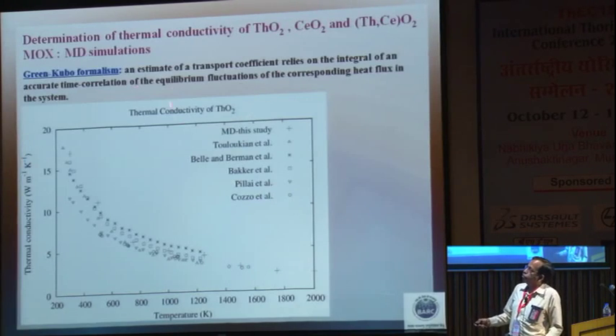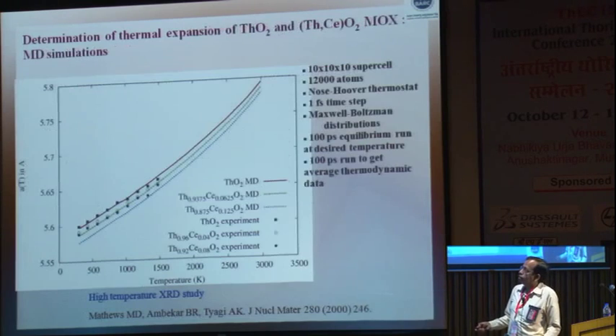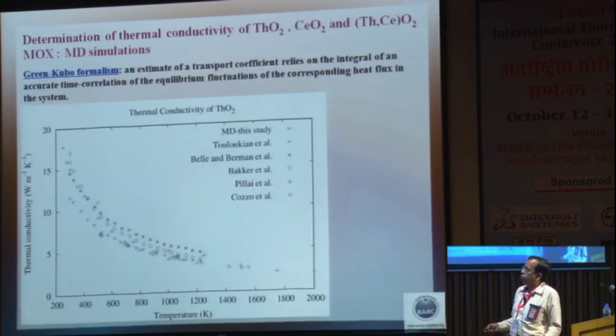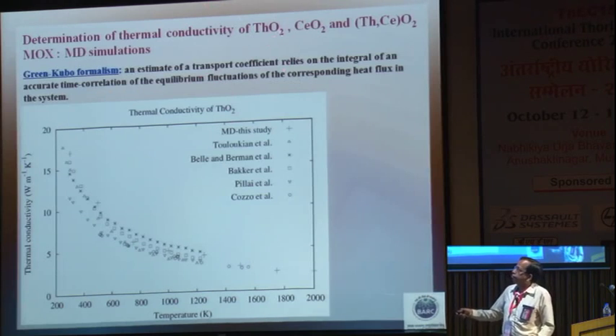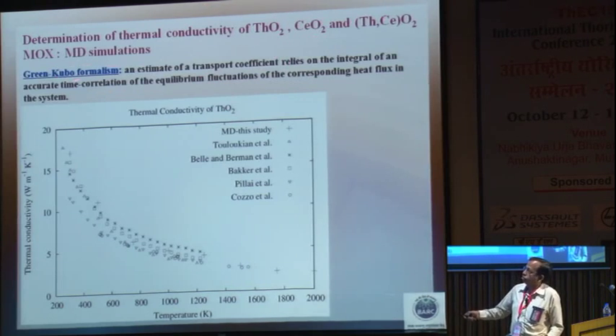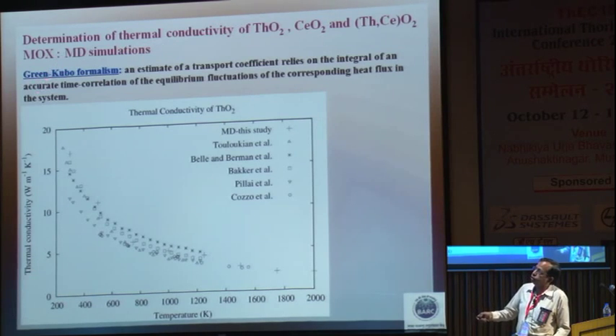Then we come to thermal conductivity. After having discussed the thermal expansion in the previous slides, we now come to thermal conductivity of the individual oxides and the mixed oxide by MD simulation, because these in the earlier section were estimated experimentally. We are determining it by MD simulation, and for thermal conductivity one has to use the Green-Kubo formalism, which means an estimate of a transport coefficient relies on the integral of an accurate time correlation of the equilibrium fluctuations of the corresponding heat flux in the system.